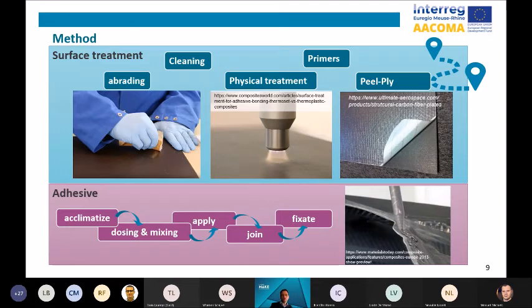Primers are also widely used. Primers create a link between the adhesion from the substrate to the primer and from the primer to the adhesive. But be aware that a primer can become the weakest link when not properly used. For example, when you do not wait long enough for the solvent to evaporate, or when you use a too thick primer layer. And always choose your primer together with the adhesive. The primer is designed for a specific adhesive.